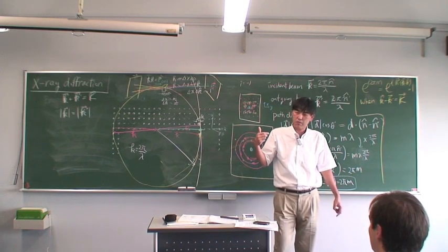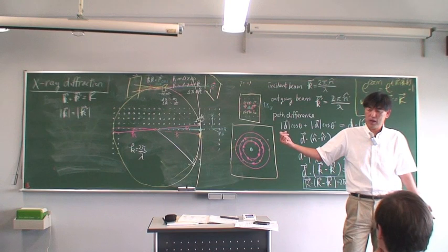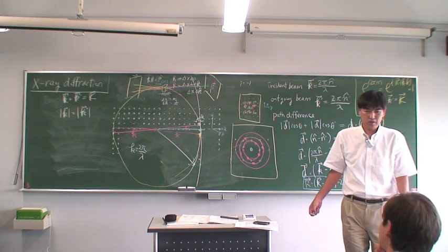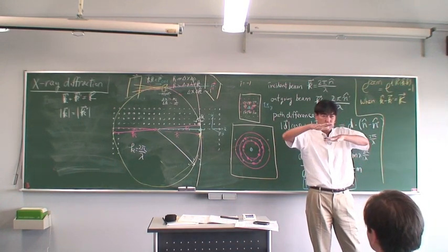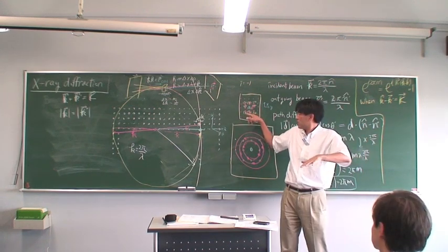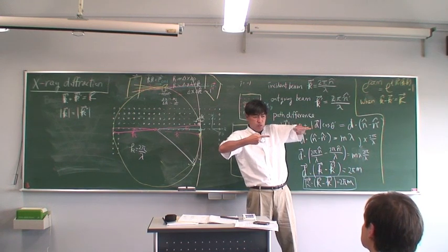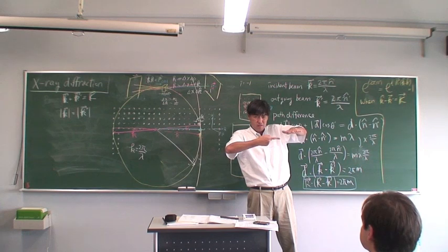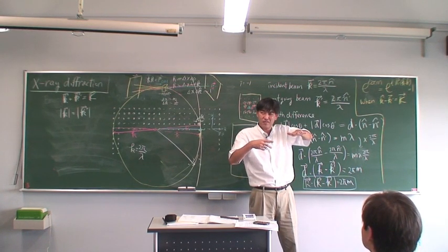So in that sense, Bragg condition is not always true, but Laue's condition gives you more practical solutions. Do you understand the discrepancy? For the 1, 0, 0 plane, I have light coming in like this, and I have many 1, 0, 0 planes parallel with the light. In this case, Bragg condition says there's no diffraction. But there is.